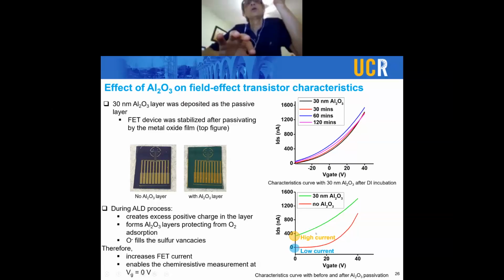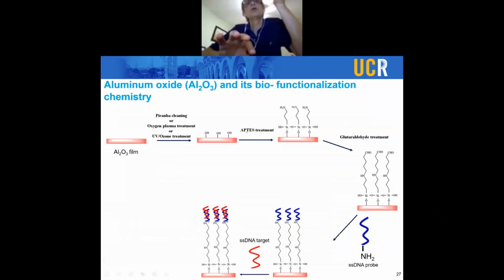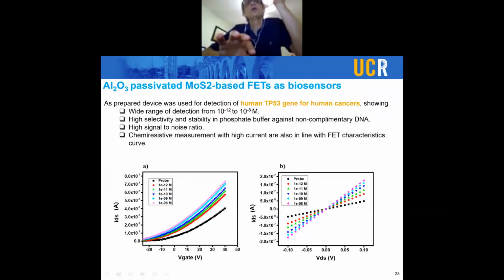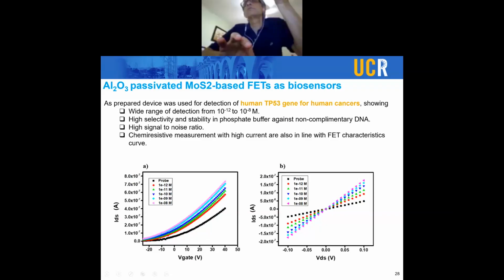We used the silanization using aminopropyl triethoxysilane, and then using a bilinker called glutaraldehyde, attached not an antibody in this case, but a single-stranded DNA, and then used it to detect the hybridization of a complementary DNA for the P53 gene for cancer, human cancer detection. And we showed that indeed we can do measurement both ways. We can do the measurement by either FET way or the chemiresistor way. And both ways are possible.